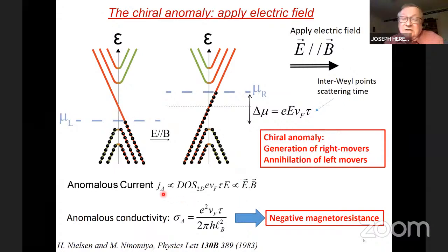And so that gives rise to an anomalous current, which is proportional to the density of states in two dimensions and the Fermi velocity at thermodynamic steady state, not equilibrium, but steady state. This acceleration due to the electric field is balanced by a scattering back, so the relaxation time comes in here, and then it's proportional to E dot B, which means that the anomalous electrical conductivity is given by these things. Because we have one over the magnetic length in the denominator, we have something proportional to the magnetic field, and this gives a negative magnetoresistance.